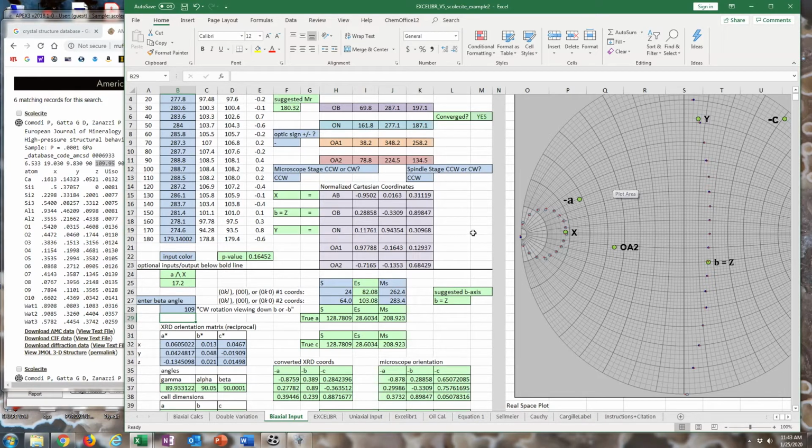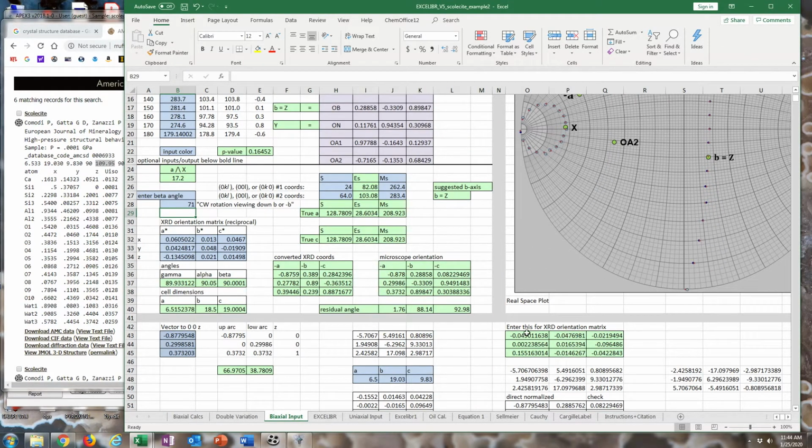It just so happens, like I explained, that that axis has similar translational characteristics as the alternative one, even though they are different directions. But this is the correct setting to use. This plot will only project upper hemisphere axes. Beta here between A and C would be acute because it's performing the rotation clockwise, but technically the C axis would be in the lower hemisphere, so that A was positive A, B was positive B, and C was positive C.